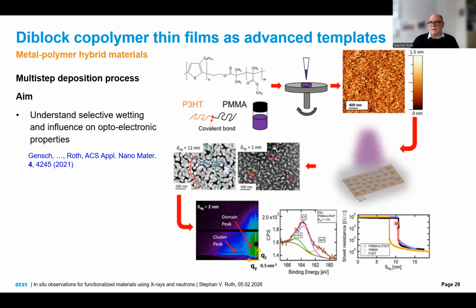This is typically the case for not so noble metals like copper. They grow in completely different structures, but we can find this out too. Once you know the structure, you can predict every physical parameter you need for electrodes. If you don't know the structure, you need at least one additional experiment to give you a derived value. And by this, you can deduce again the structure, the shape of your nanoparticles.